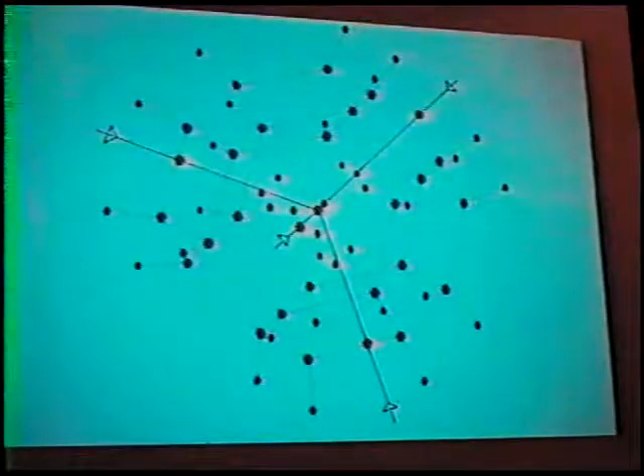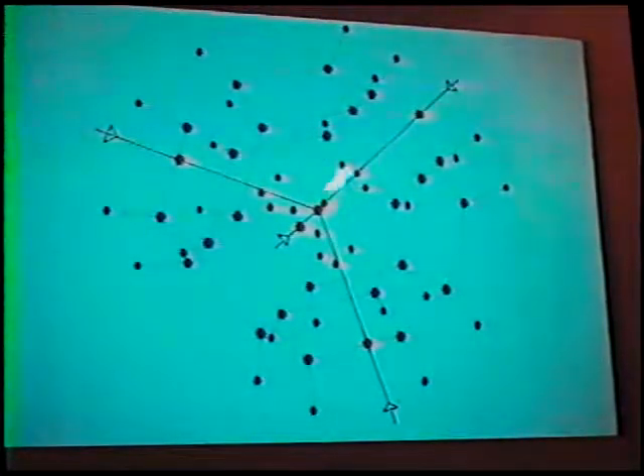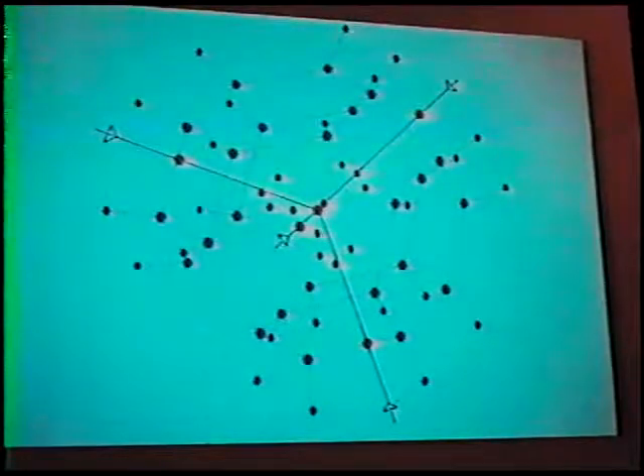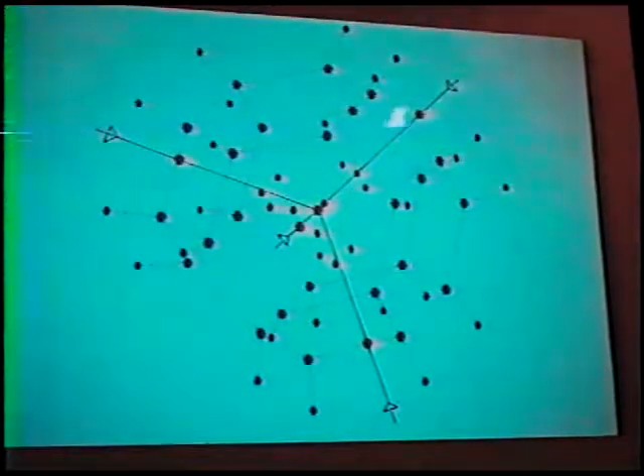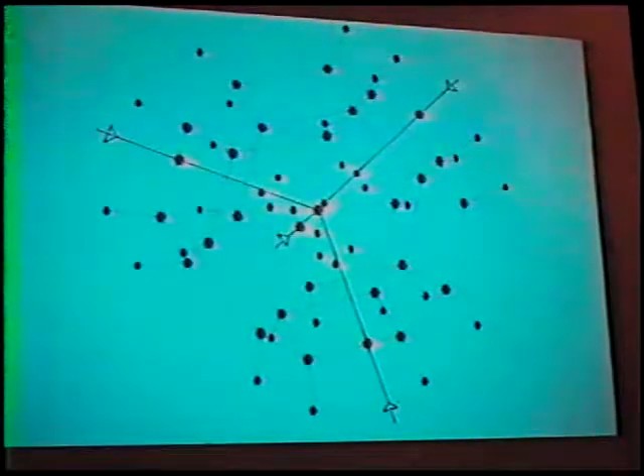This slide shows the same part of the structure at 873 degrees Celsius, but after the one normal acid leaching. Species very similar to those shown previously are detected: one atom at the center of the sodalite cage and three other atoms. However, they are not perfectly situated on the threefold axis — you can see the three representations with the symmetry axis. The last atom seen previously near the hexagonal prism is now translated further into the hexagonal prism.